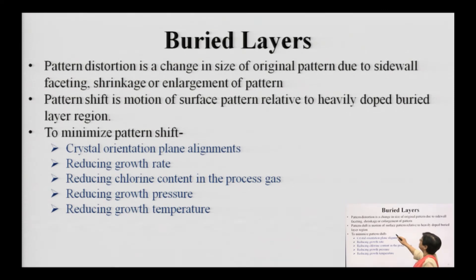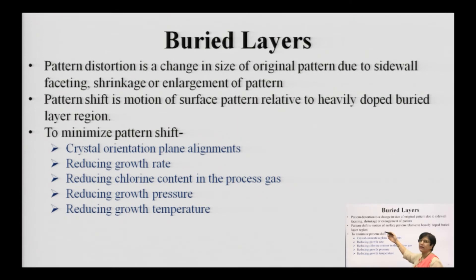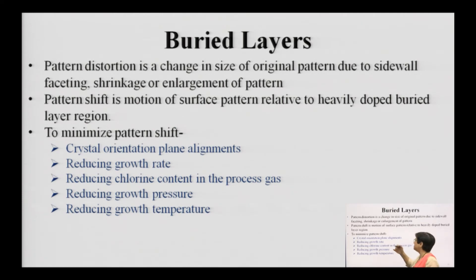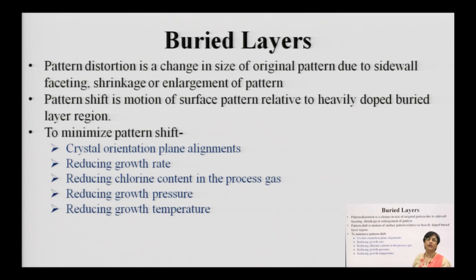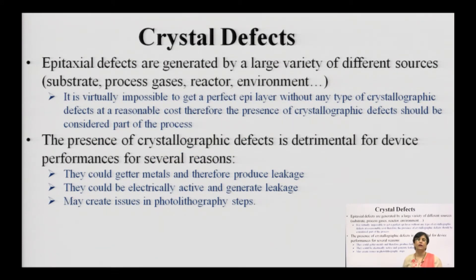To minimize pattern shifts from buried layers: check crystal alignments, reduce the growth rate to reduce mobility and improve deposition precision, and reduce chlorine content by using silane instead of silicon tetrachloride. Reducing growth pressure and reducing growth temperature are also recommended remedial actions to improve epitaxial growth when buried layers are present inside the substrate.